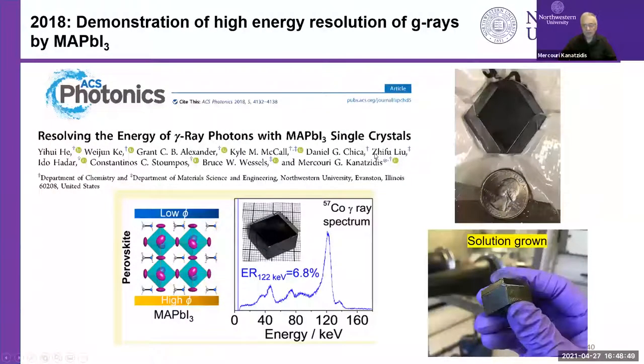We use the same asymmetric electrode device to demonstrate other perovskites that can also detect radiation, such as this methyl ammonium lead iodide. And we can grow these crystals not by Bridgman, because it decomposes, but by solution growth. And you see very large crystals are possible. And that works too. It's not as good as cesium lead bromide.